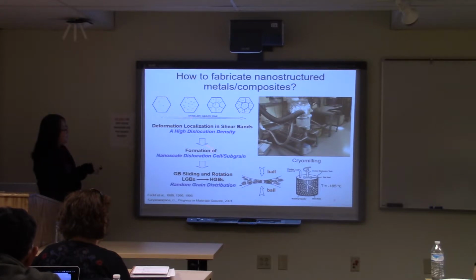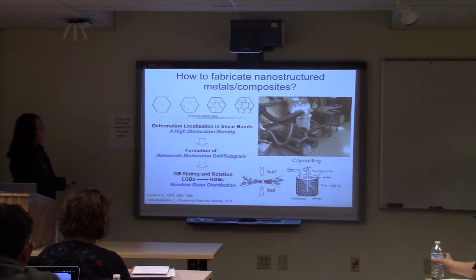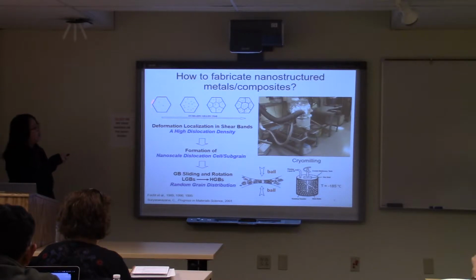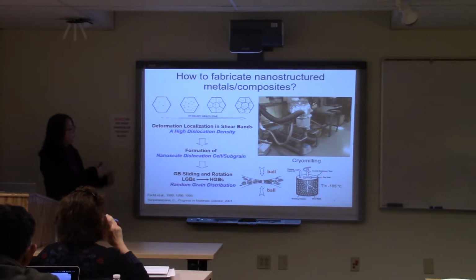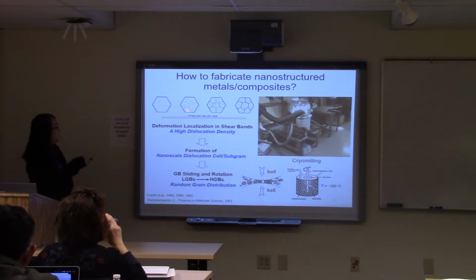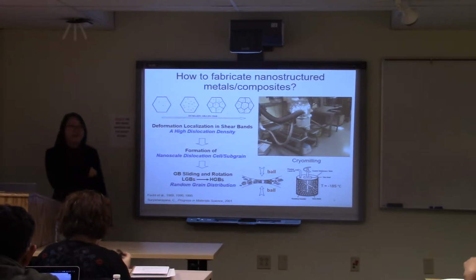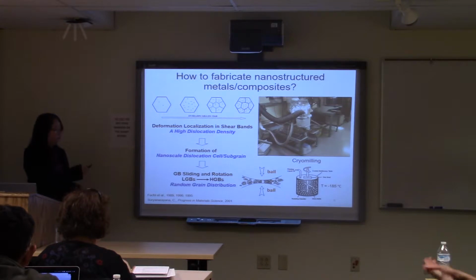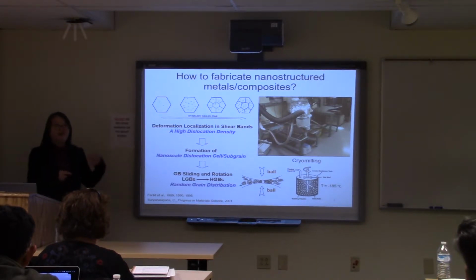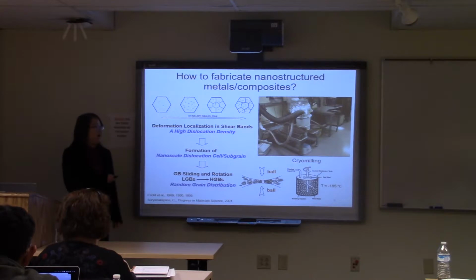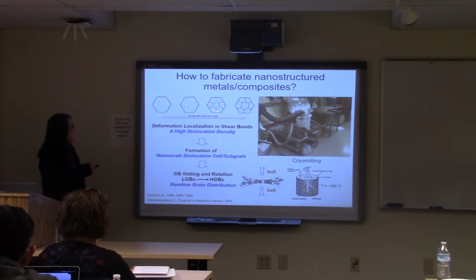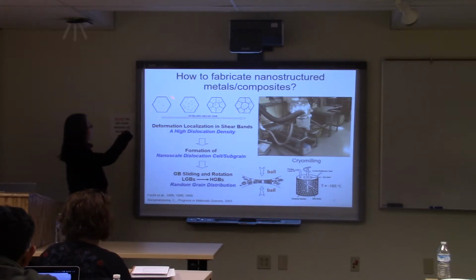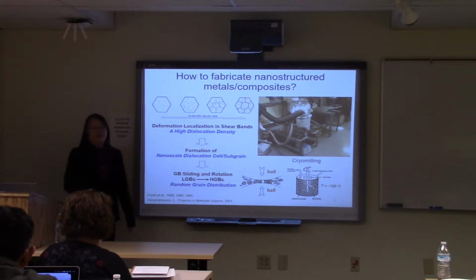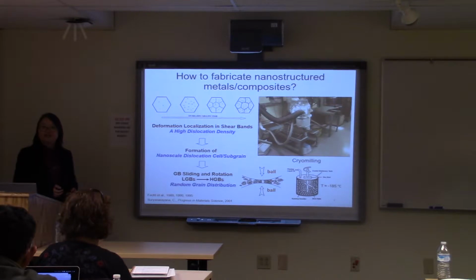This shows the three stages of how the nanostructure is created. If you start with a relatively coarse grain and deform it during the impact between two balls, you get a very high dislocation density within the grains. As the milling time goes on, those dislocations evolve. They either annihilate each other or pile up and form cells, and then transform into more equilibrium boundaries. So you convert the original coarse grain into a grain that now has several grains inside. You introduce grain boundaries into a particle.